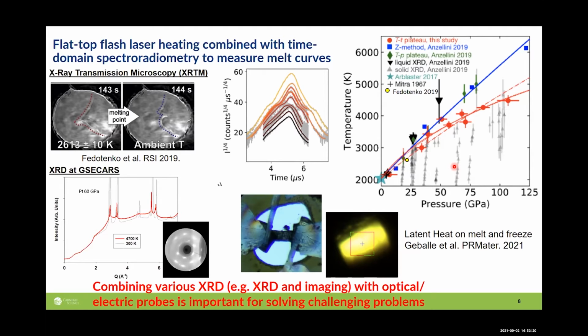And a number of speakers at this workshop already addressed this issue, trying to determine the melting curve, for example, by looking at the diffuse scattering like we did here in the case of platinum. Platinum is a great model sample because there are good theoretical predictions and also a lot of measurements. So you can clarify your experimental techniques.